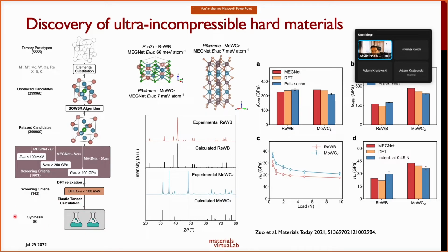And finally, my colleague at UCSD, Professor Jian Luo, then went ahead and tried to synthesize them. And he actually confirmed all 8 of those materials that he tried. But here are 2 examples of new materials that came out of the synthesis: this rhenium tungsten boride and this molybdenum tungsten carbide. And here is the comparison of the experimental XRD as well as the calculated XRDs. And you can see that they are in good agreement with each other.